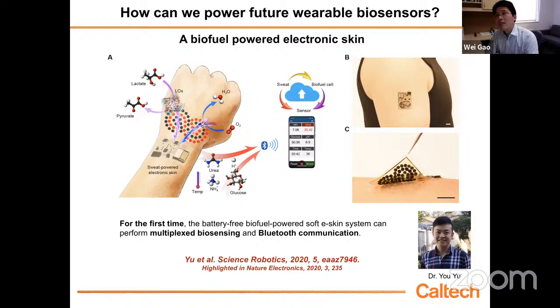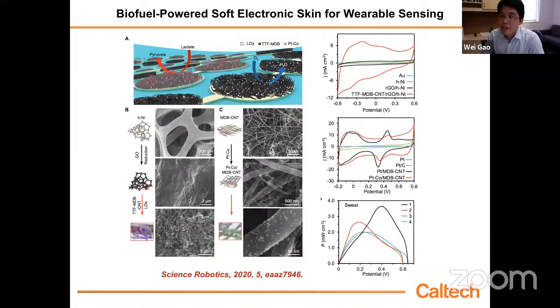Typical biofuel cells suffer from low power density and poor stability. We actually address this problem by using nanomaterial innovations. In this case, we have two electrode arrays. The bioanode is an enzymatic anode with lactate oxidase to catalyze lactate oxidation to get electricity, right? On the anode side, we are using a 3D nickel structure. We coat the nickel structure with graphene oxide, and we then coat the graphene oxide surface with a carbon nanotube network. We actually enhanced the surface area by 3,000 times. In this case, we can get a very high power.